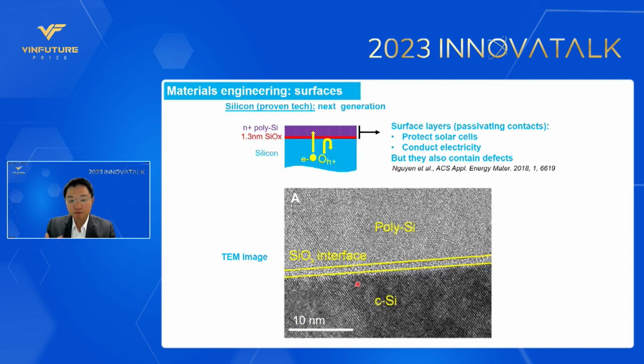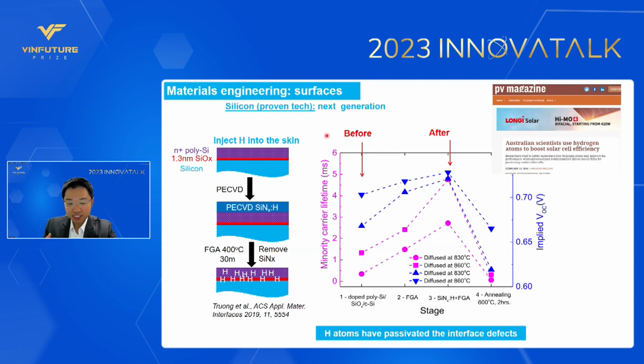We also develop techniques to improve the solar materials. First, for the surface of silicon solar cells, our team is working on the newest technology we call the passivating contact. Basically the silicon substrate, then we cap it with a stack of a very thin silicon oxide layer, less than 2 nanometers thin, and a poly-silicon film. So this stack can serve two purposes. First, it can protect the solar cell. Second, it can conduct electricity. However, the stack also contains defects. And we develop a technique to inject atomic hydrogen into the contact structure to deactivate those defects.